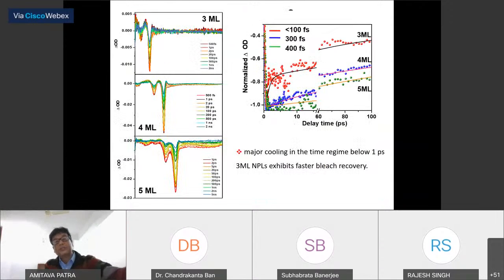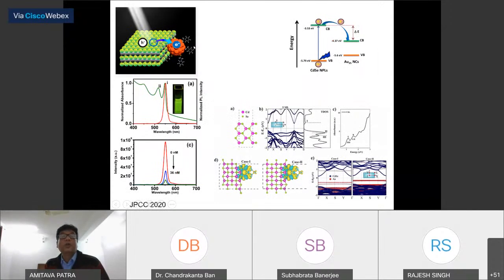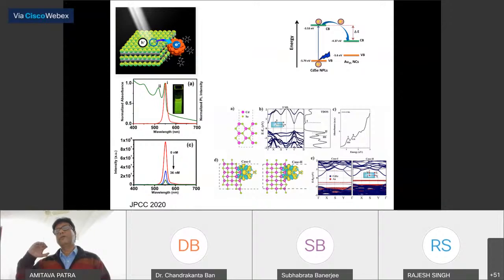And recently we developed for 3 layer, 4 layer, 5 layer structure, the ultra fast cooling also you can control for 100 femtosecond. Why we are interested? We develop different system also with the gold cluster, because by theoretical understanding we try to understand what is the electronic interaction with the gold cluster or molecular system with the 2D structure, what kind of band gap. We have seen that the Fermi level will change and it goes from close to the valence band to the conduction band, and that will create the charge transfer.